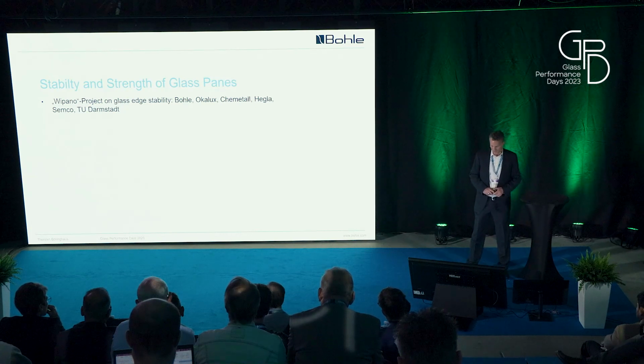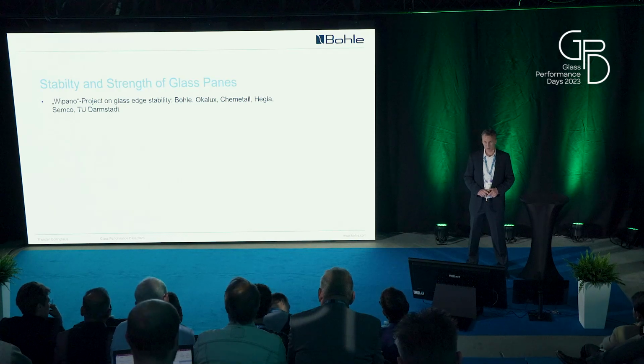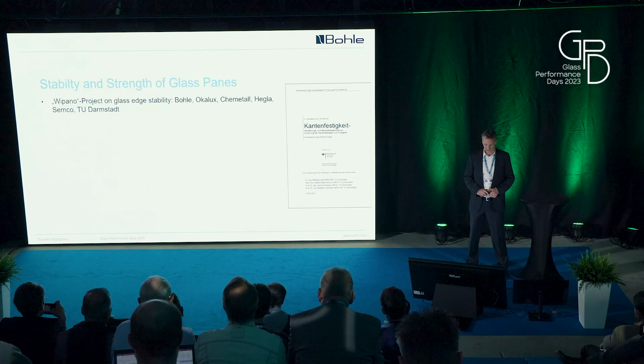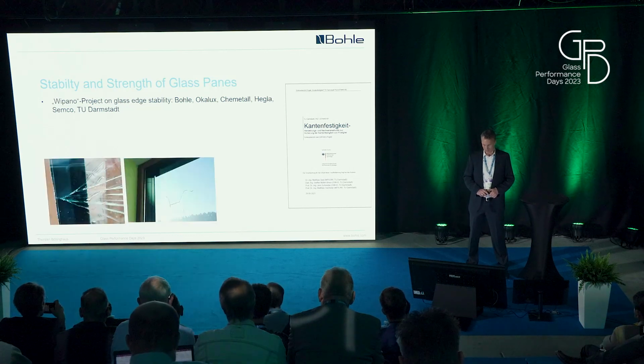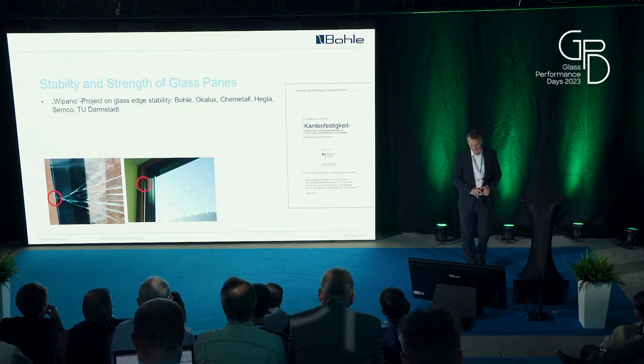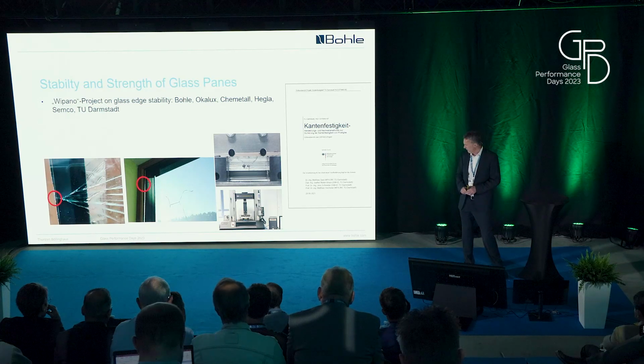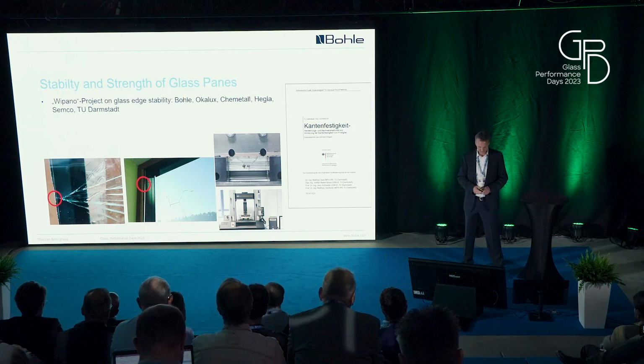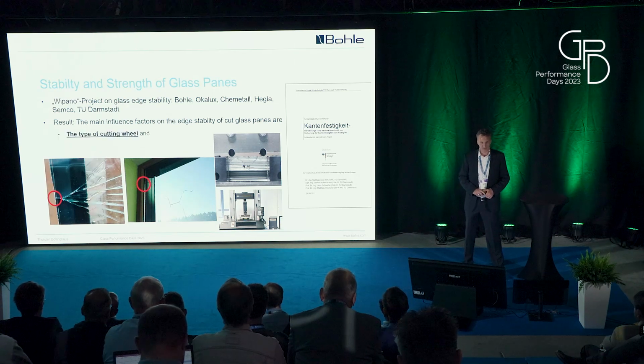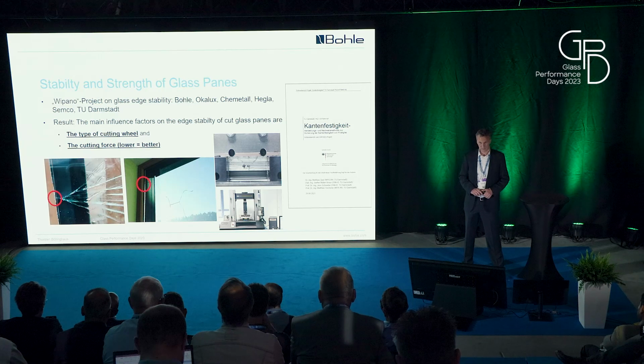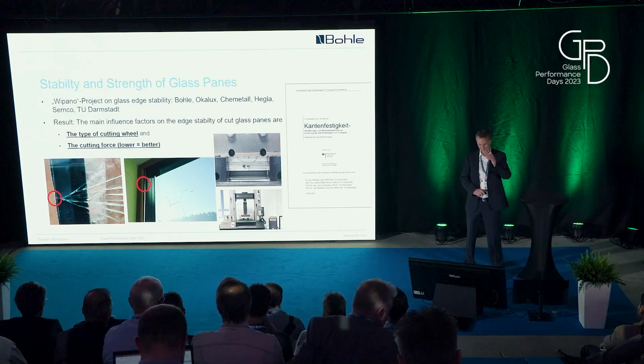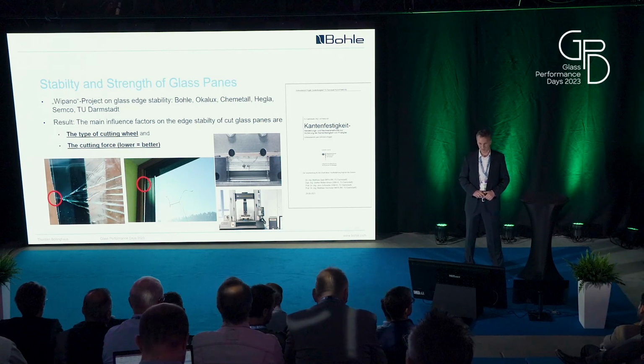Matthias Seel this morning talked about a project done at the University of Darmstadt together with Bohle and other companies, where edge stability was analyzed and the influences you can have on it. For those who did not attend his very interesting talk, the result of the study, a statistical study between all the parameters you can have in glass cutting and the result on the 4-point bending test, which gives you an indication of the edge strength of the glass, is that the main influence factors on the edge stability are the type of cutting wheel and the cutting force. You need a certain cutting force for sure to do the cutting, but above that level, a lower cutting force is better for the edge stability of the glass.